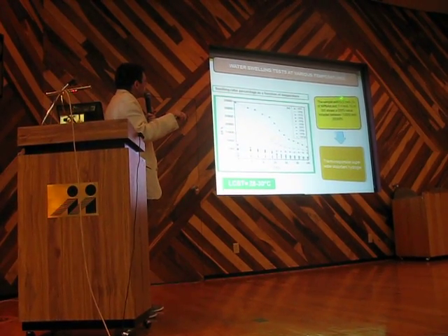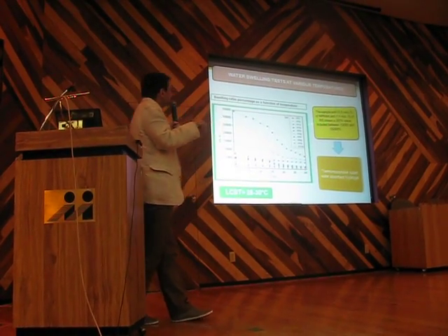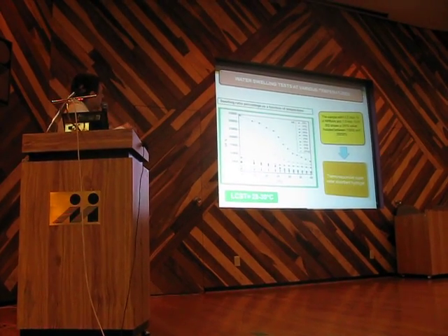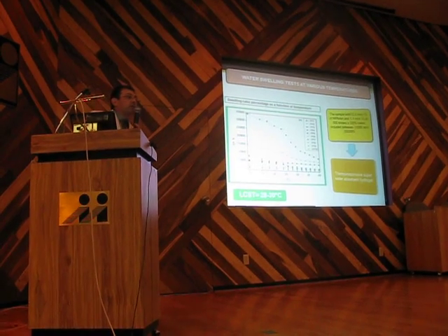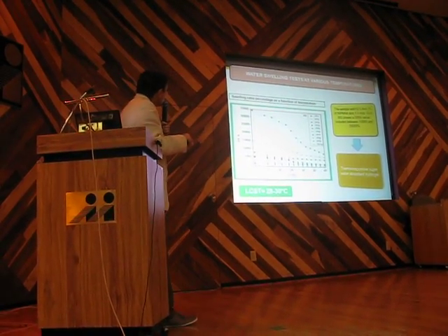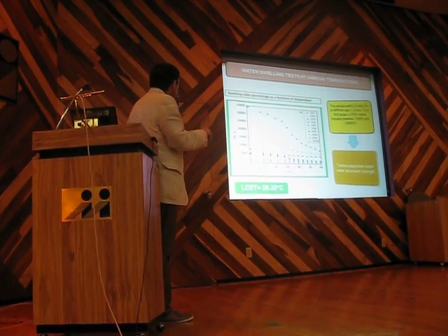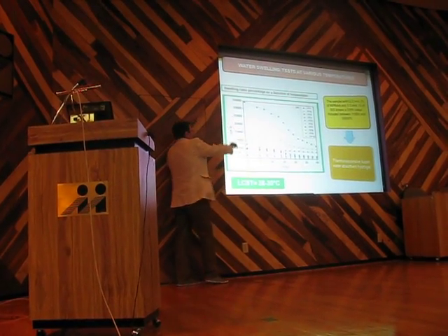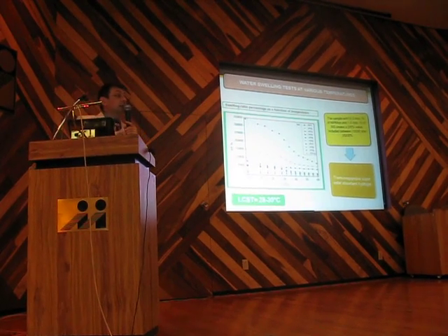It's the sample with 12.5 mol% of NIPAM and 1 mol% of crosslinker. We reached this very high value of swelling ratio, 35,000%. While using NIPAM alone, we are more or less in this zone. So we have a very high increase of the swelling ratio by using this comonomer.